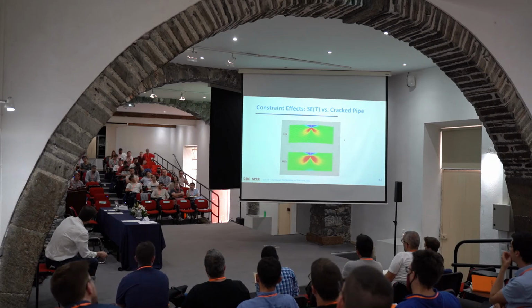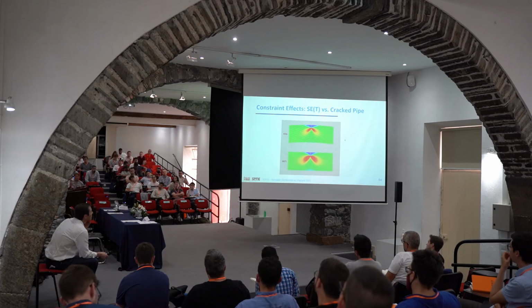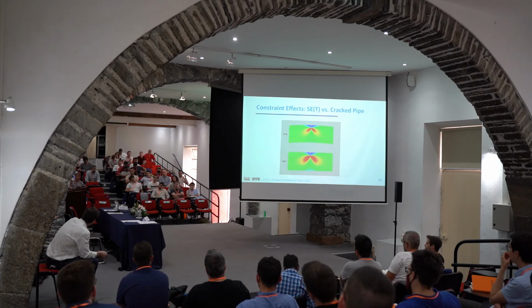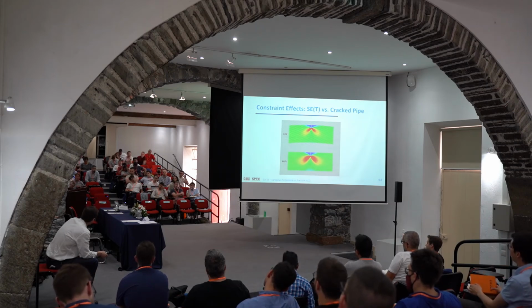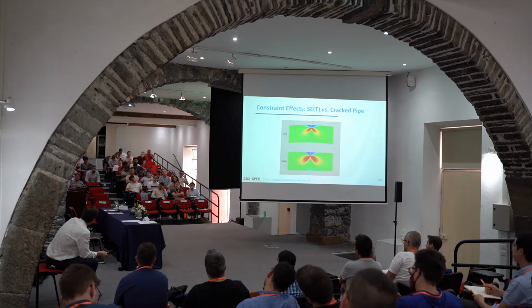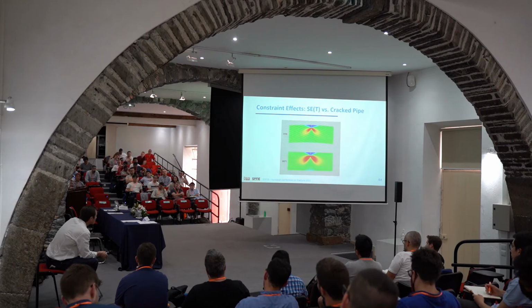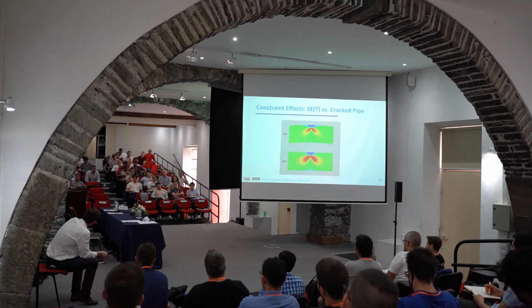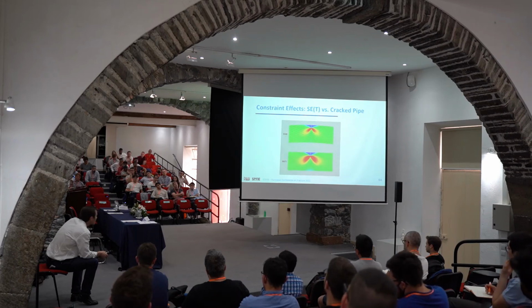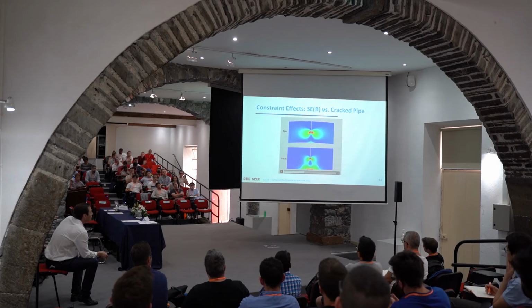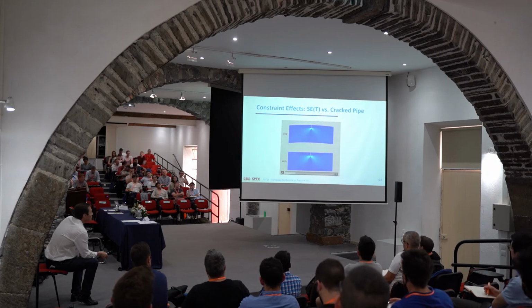I don't have it here, but if you go to Ted Anderson's fracture mechanics book, are you familiar with Ted Anderson? You're going to see the plastic shape on the plane strain, high constraint deformation. It has a very typical shape. When the triaxiality is smaller, the plastic zone starts to tilt. So actually you can see here, this is the SE(B). The SE(B) is like this. Here, see how different it is? And you can see clearly the development of a very negative T-stress.